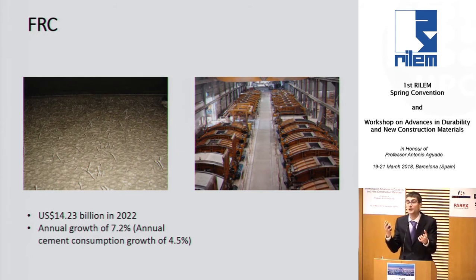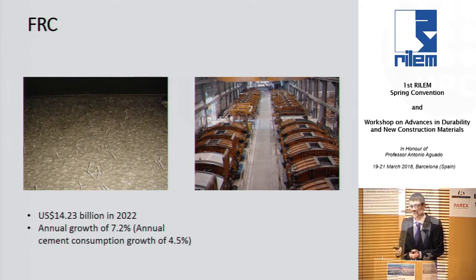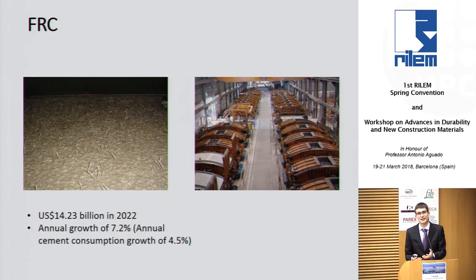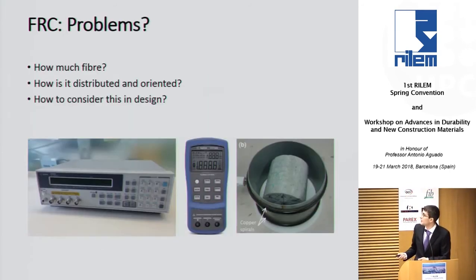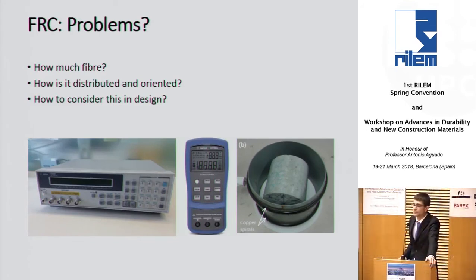And the performance might not match from the small-scale element that you test in the lab, a very small beam, and the real-scale element. Because the fiber distribution is different, mostly. So one of the challenges here was to be able to measure in a very simple way this fiber content, this fiber orientation in the elements, right? In the segments, the big elements that we are going to produce. So we have developed different strategies of doing it, right?